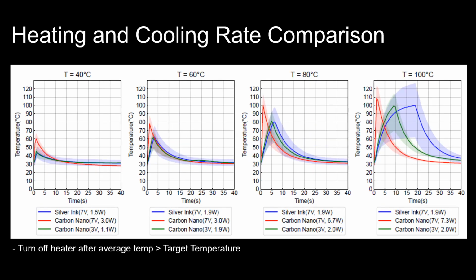This graph shows a comparison of the heating and cooling rate at different target temperatures. Since carbon nanomaterial has high thermal conductivity, both heating and cooling rates are better than silver ink, demonstrating the high power efficiency to reach the target temperature at low voltage. The narrower color band of the carbon nano heater also indicates a good uniform heating capability.